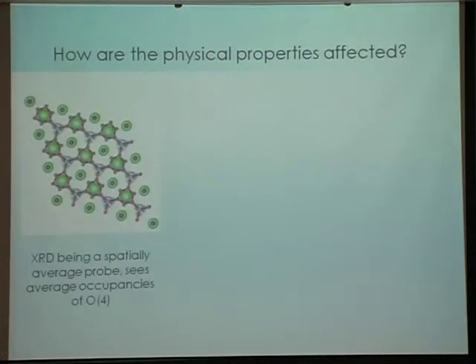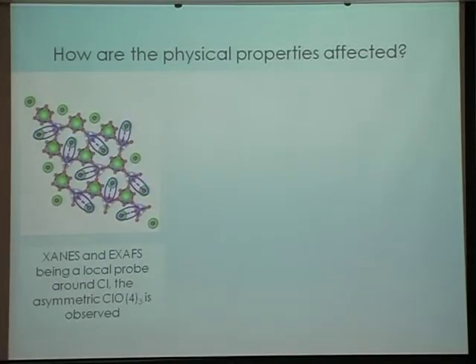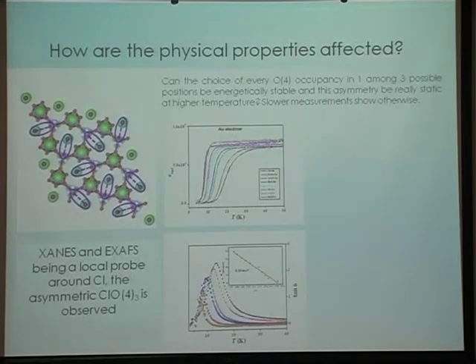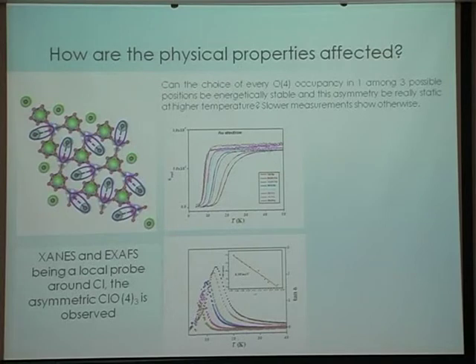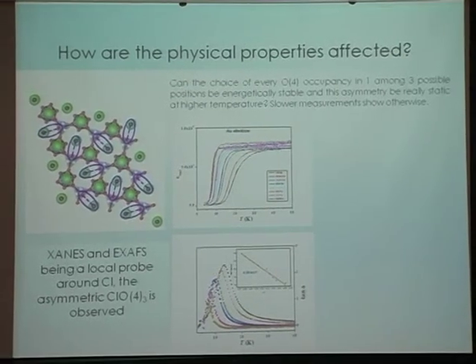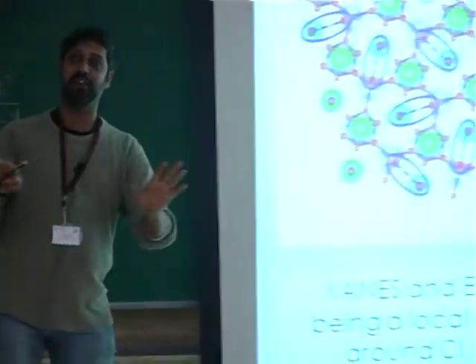There could be another interesting manifestation of it. XRD, being a spatially average probe, looked at the average. EXAFS gave something like a static distortion, but all of them are very fast to connect the two tetrahedral cobalt. So when the cobalt-oxygen-cobalt bonds are fluctuating and when they get frozen, there will be an indication on magnetism too, and that's precisely what you find. So I would like to call it a covalency-driven magnetodielectric in a way.